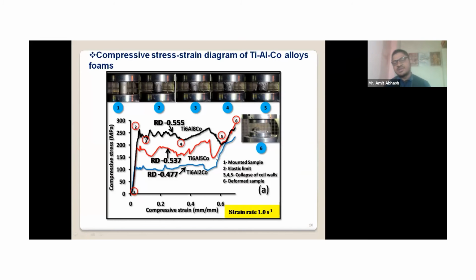So this is the compressive stress strain diagram. The first point shows the initial stage when the sample is mounted. In this entire process we used a camera and monitored it during the compression test. This is the stress strain diagram of the metal foam, and we can see that as the cobalt percent increases, the strength increases. This is the compressive yield strength, the yield point.